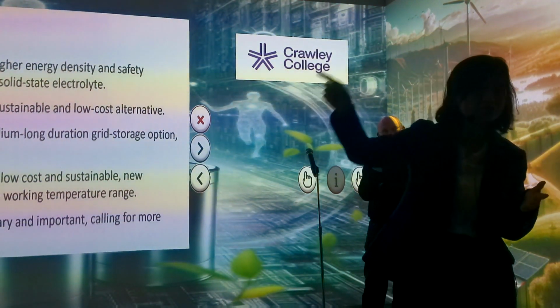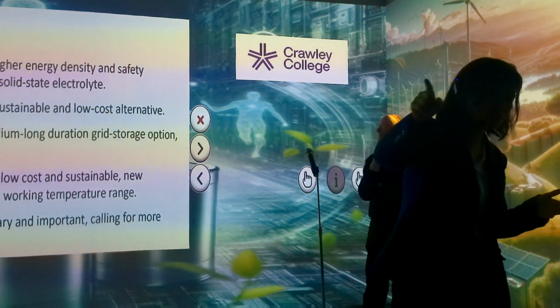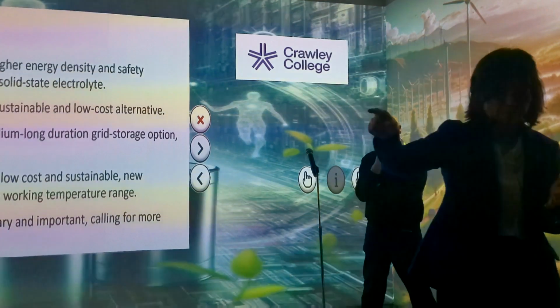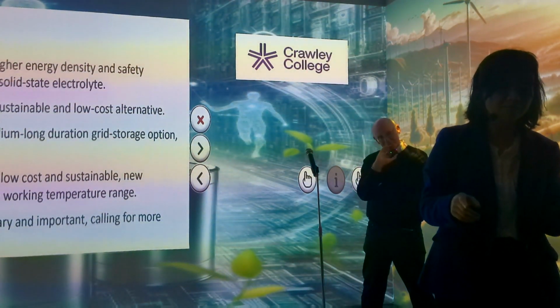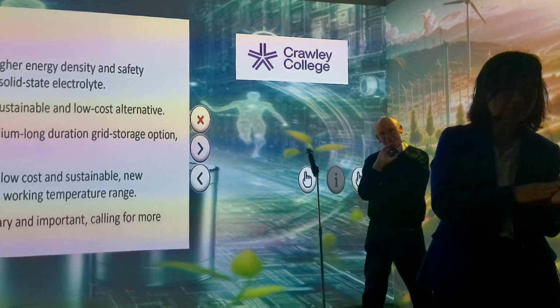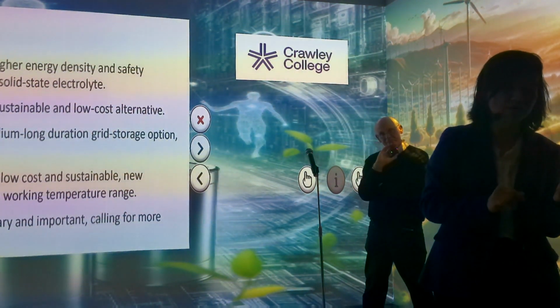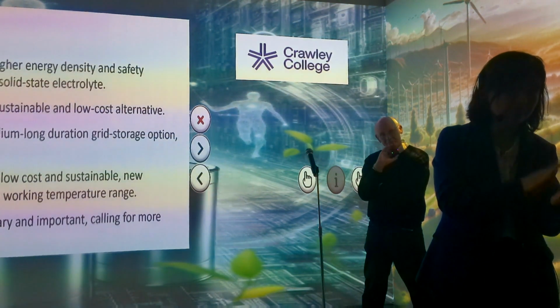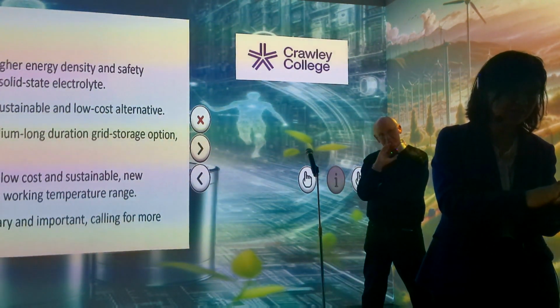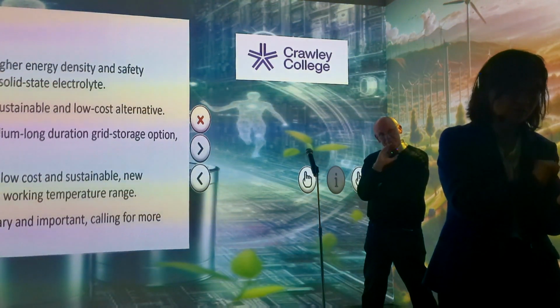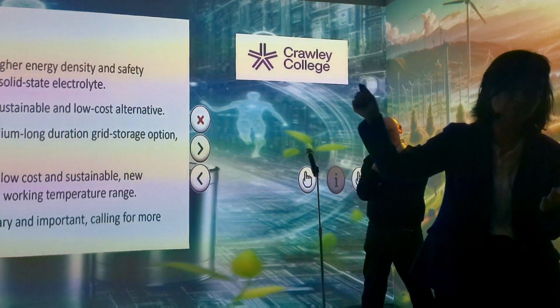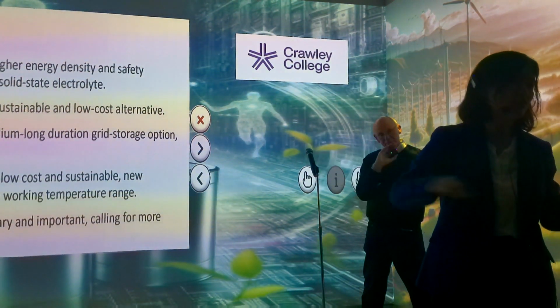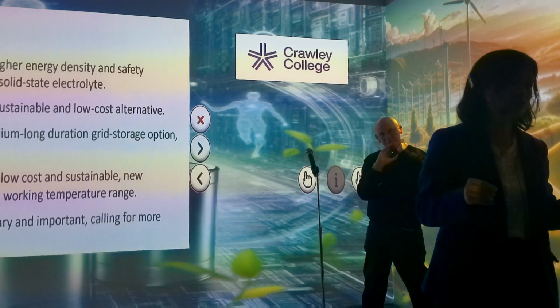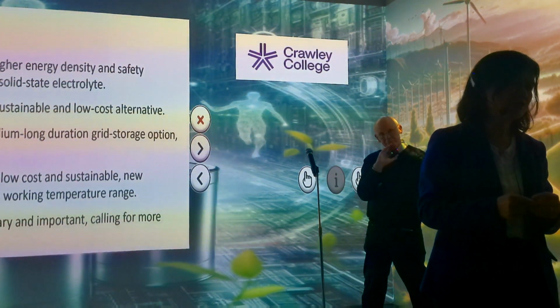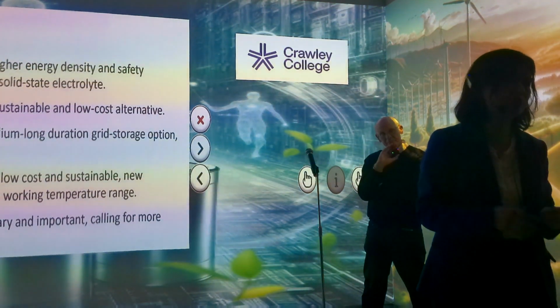And also, when you move the lithium ion to the anode, even for graphite, you can have a plating phenomenon happening there. If you have a lot of lithium ion going to the anode at a low temperature, particularly, the dendrite can even grow with graphite. And once you have a dendrite, it pierces through the separator, reaches the cathode and short circuits. So a lot of processes are happening, and therefore the battery management system is very important to ensure that the batteries operate very properly.